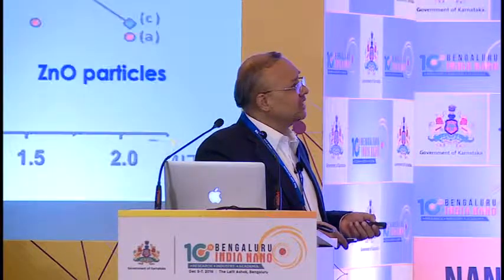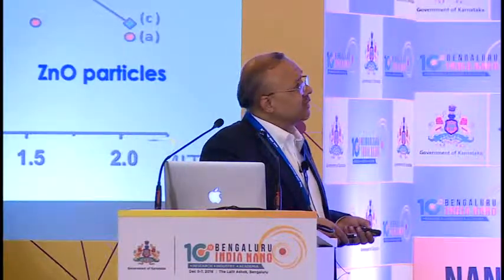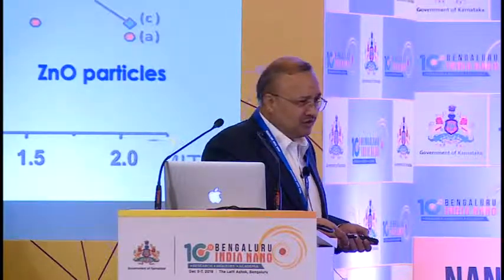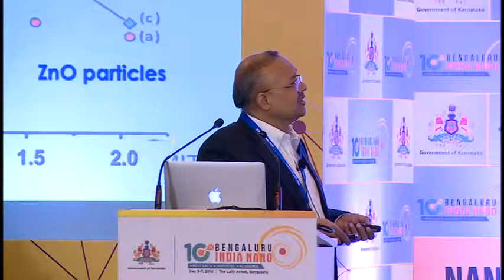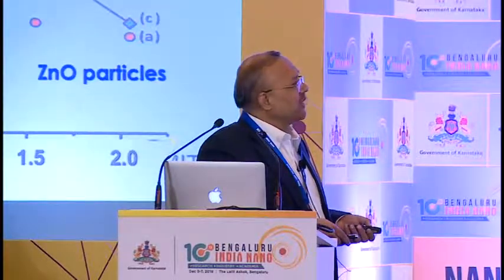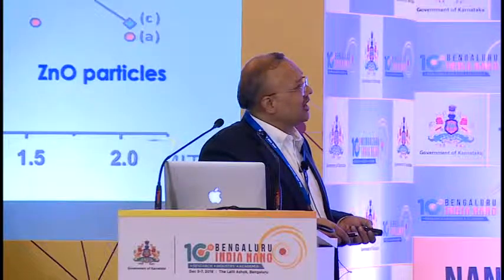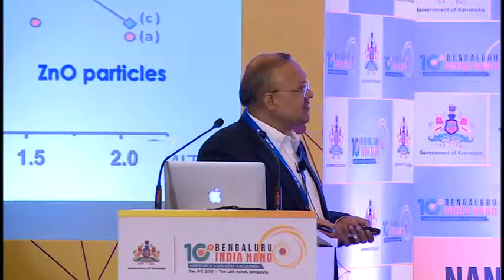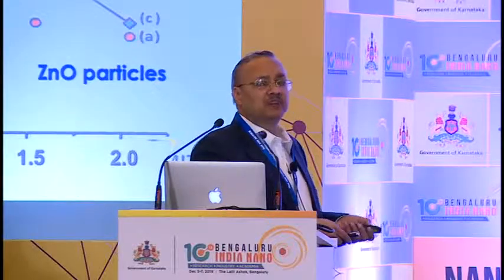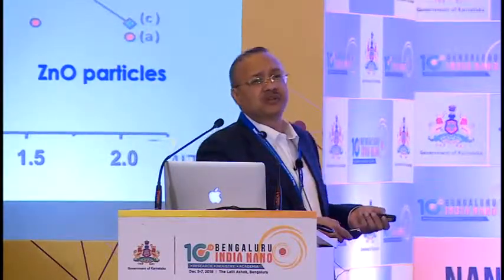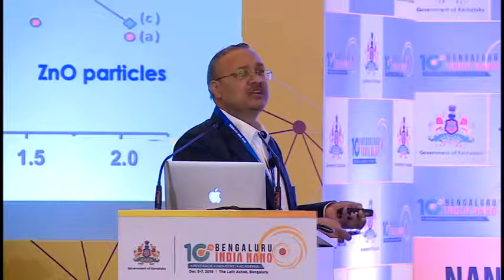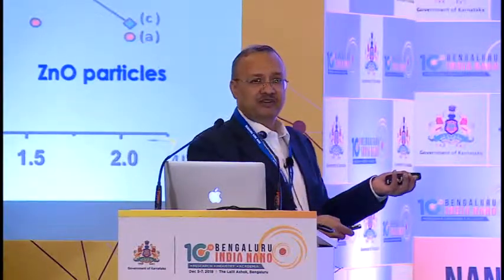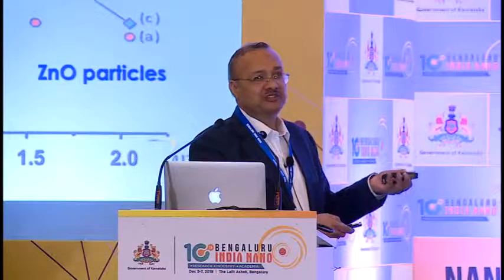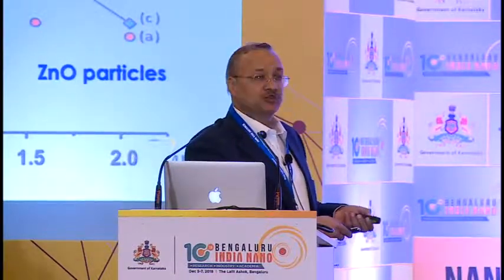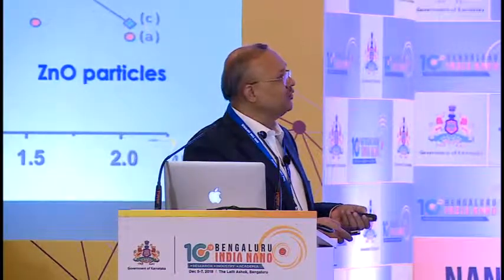And once you can create those things, what we see as we increase, these are 3 aspect ratios, ZnO particles, I don't think you can see this curve, but these points are there. And then ZnO rods, and then ZnO wires. And we can add them in very, very small quantities, 0.5% to 1%, 1.5%. Actually, if we can do really good mixing, we can probably go below 0.5%, but we all know nanomaterials are very difficult to disperse and separate once created. But we still do. So all the technology here is on dispersion, how to disperse them.